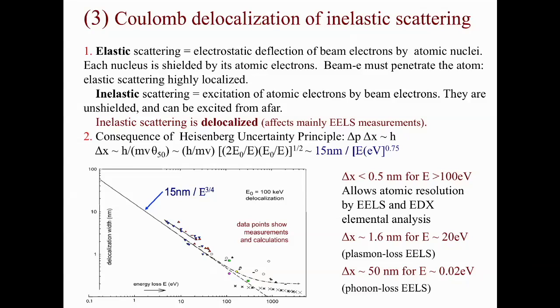We can use the Rayleigh resolution formula to estimate the diameter containing 50% of the scattered electrons. The result is a simple formula that tells us that this diameter has atomic or subatomic dimensions for high energy losses, like the ionization edges used for elemental analysis. So atomic scale elemental analysis is possible by EELS or EDX spectroscopy. But the 50% diameter becomes a few nanometers or even tens of nanometers for the lower energy losses that are sometimes used for EELS structural studies. And reducing the specimen thickness has no effect on the Coulomb delocalization.